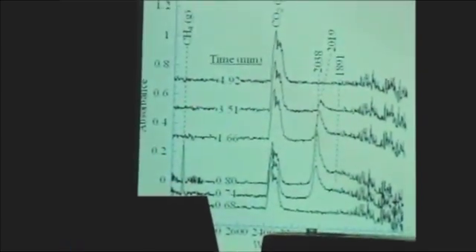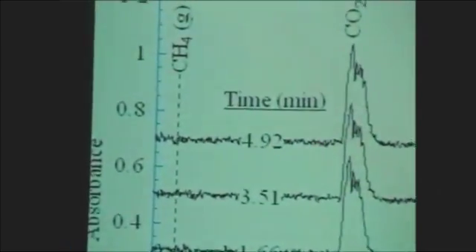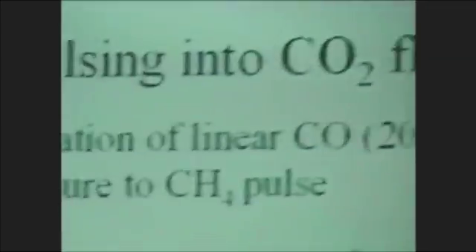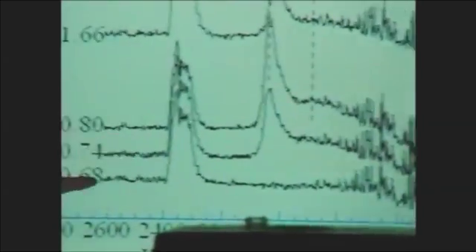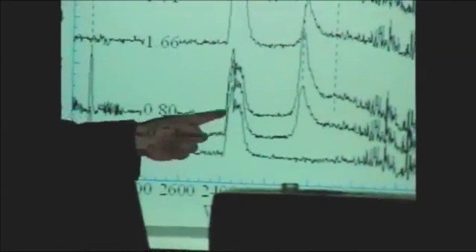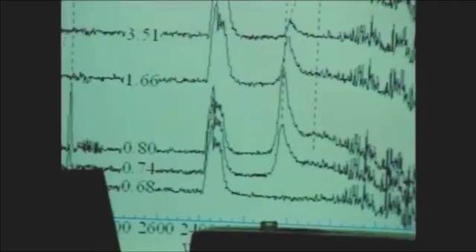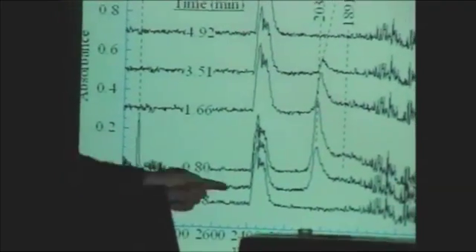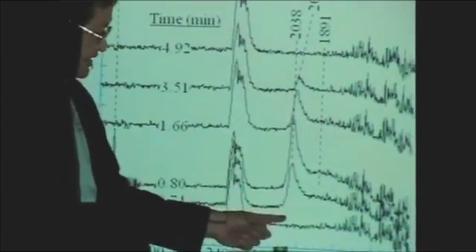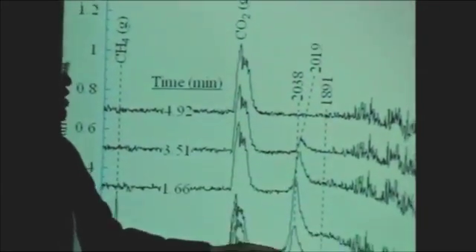In this case, we flow the CO2 over the catalyst surface, then pulse 1 cc of methane into the reactor. Let's take a look at what happened when we pulse this methane into the CO2 stream. If we pass the CO2 through the catalyst surface, we don't see CO2 adsorbed, usually CO2 doesn't adsorb on the catalyst surface. We see the CO2. Once we pulse 1 cc of methane in and the methane enters the reactor, we start to see the methane promote the formation of adsorbed CO.